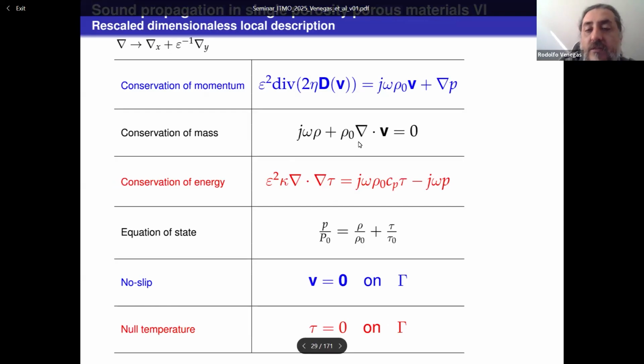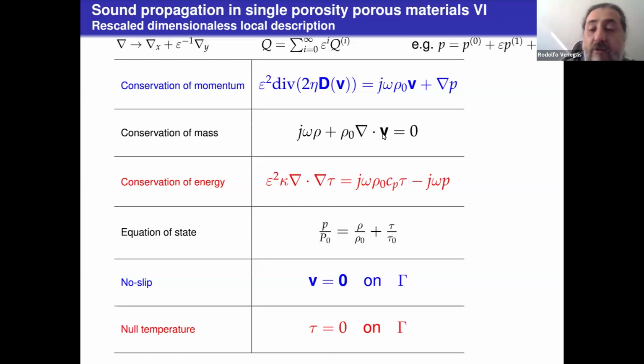The divergence doesn't change locally, but rather macroscopically, and therefore there is no scaling here. And for the temperature, we have a conduction term with an epsilon squared rescaling. Then we say that every variable is a power series in terms of epsilon. For example, pressure is equal to the leading order pressure, P0, plus epsilon times the corrector of pressure, and so on. We insert this series into this equation,